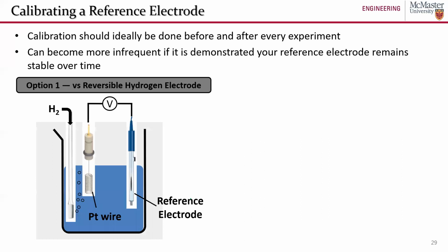And to answer the question of how one can do it, there's a few different ways. I'm going to talk about 2 on this slide. The first is by calibrating your reference electrode versus a reversible hydrogen electrode. A reversible hydrogen electrode is essentially a platinum wire immersed in the electrolyte that you're using with hydrogen bubbled over it at 1 atmosphere.